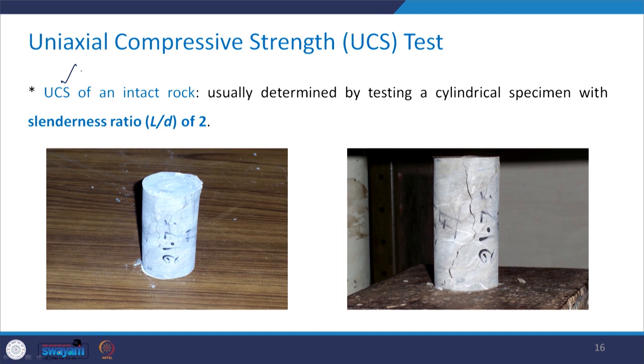So here I have put 2 photographs of specimens which were tested in the uniaxial compressive strength condition. The UCS of the intact rock is determined by testing a cylindrical specimen with a slenderness ratio of 2. Slenderness ratio means that if this is its diameter and this is its length, then the length to diameter ratio is 2. So these were tested, and you can see how the failed specimens look.